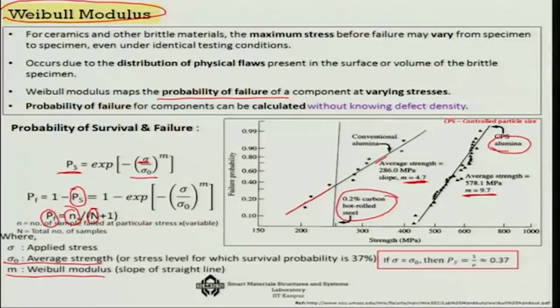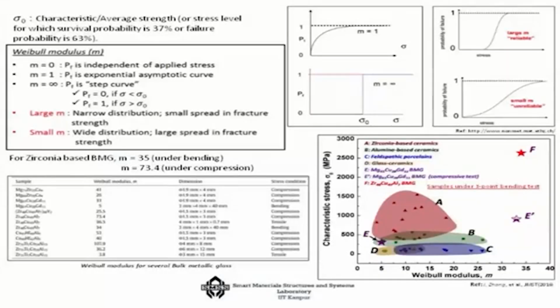To do that, we have to keep track of how this Weibull modulus is going to change as I introduce various reinforcements, composites, etc., or change parameters like porosity, making it more uniform, and increase the value of the Weibull modulus. You can see it here, for example, that this is the Weibull modulus m equals 1. For m equals 0, Pf is independent of applied stress; for m equals 1, Pf is an exponential asymptotic curve; for m equals infinity, Pf is the step curve.